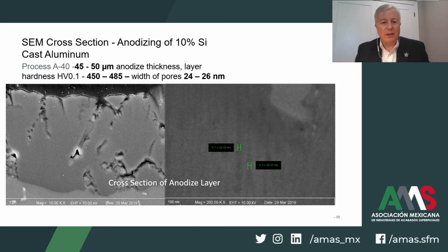As shown in this slide, with increased oxide thickness and a much better defined, more uniform pore structure ranging from 24 to 26 nanometers, shown at 200,000 times magnification, the ability to provide higher performance with depth of color, range of color, shade of color that will have improved resilience from the improved hardness. There's less fading out of the color both during the processing and while the part is in its final environment, offers many benefits for high silicon cast alloys.